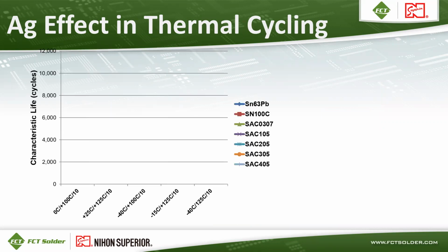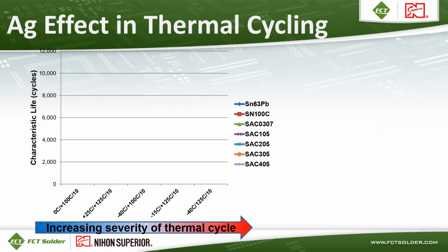So what effect does silver have on thermal cycling of these alloys, or how does silver help with reliability? Here's a chart of characteristic life on the y-axis with different temperature ranges of thermal cycling on the x-axis. And as you go from left to right, the temperature ranges become more severe, more difficult. So we're going from 0 to 100 C at the left side of this graph to -40 to +125 C at the right side of the graph, and with some temperature ranges in between. So the characteristic life of tin lead is shown there in the blue diamonds. And you can see that that life is stable regardless of thermal cycle.